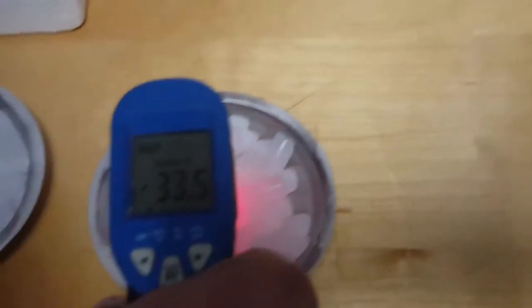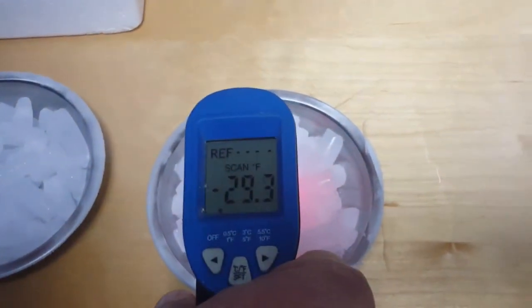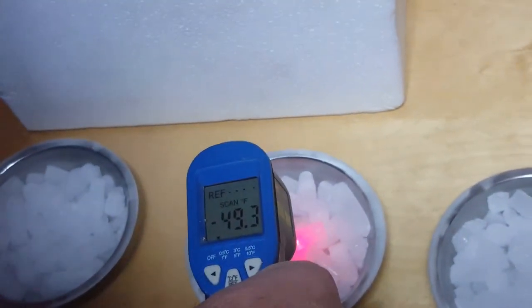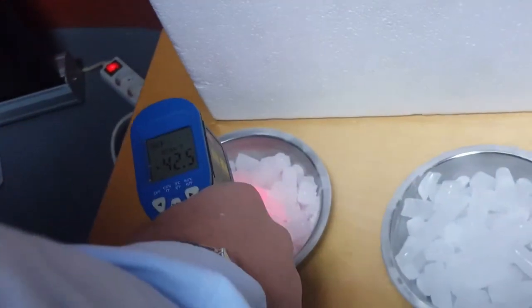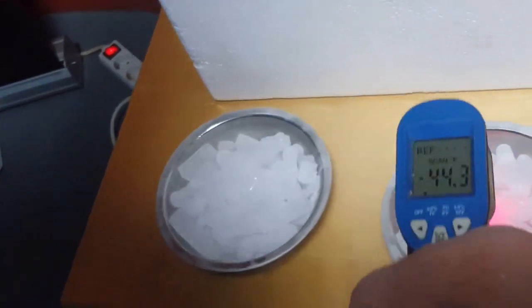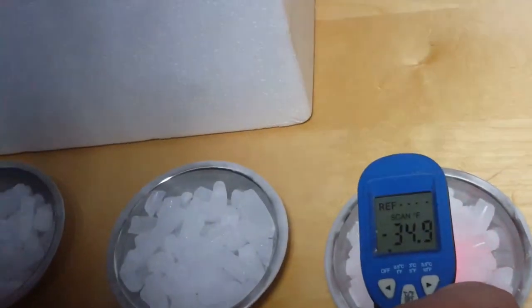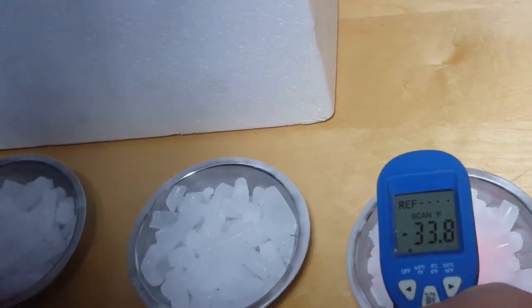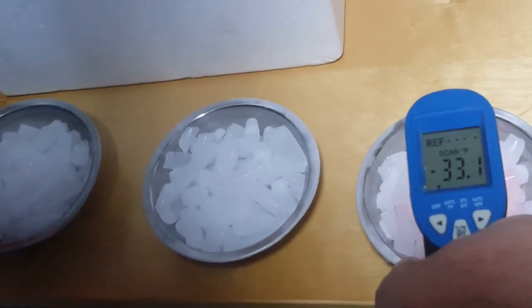And we can see the bottom side of that control sample was clean of condensation because it was continually exposed to the dry ice. And then when we measured the temperature of the dry ice to finish off, we can see that the coated samples actually protected it from warming up compared to the control sample, which is exposed only to the metal sheet and allowed the ambient temperature of the room to warm up that dry ice.